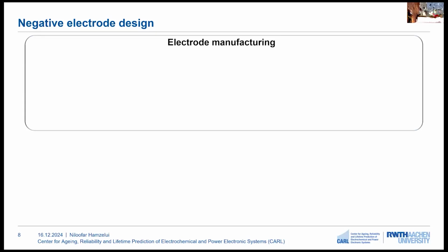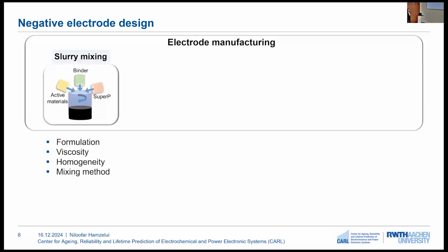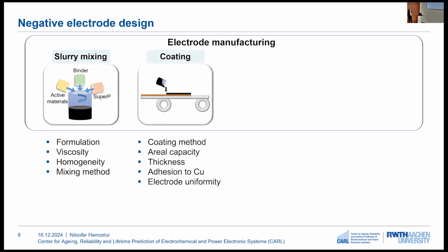For designing the negative electrode, we start with the electrode manufacturing. The first step is the slurry mixing. This is where we are mixing the binders, active materials, and conductive additives together. Here we can control the formulation of this slurry, the viscosity of the slurry, and the homogeneity and mixing methods, which can have an effect on the next step, which would be the coating of the electrode.